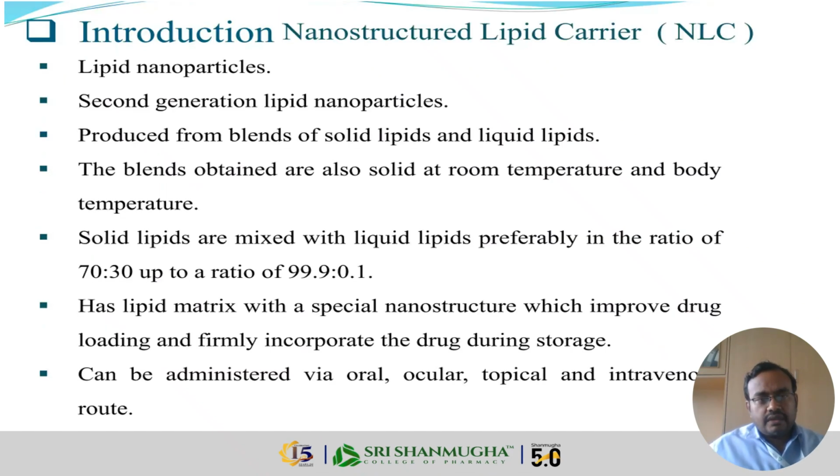So nanostructured lipid carriers, it contains the lipid nanoparticles. It is a second generation of lipid nanoparticles. The product is from the blends of solid lipids and liquid lipids. The blend obtained is also solid at room temperature and body temperature. Okay, so the lipids should be solid at body temperature as well as room temperature. The solid lipids are mixed with the liquid lipids, preferably in the ratio of 70 to 30 percentage,